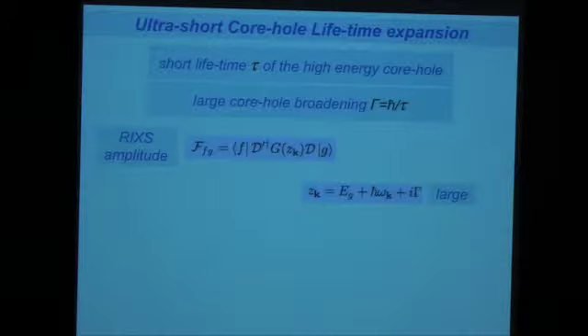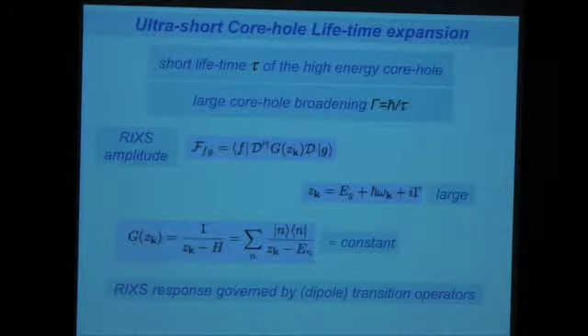If I look at the RIXS amplitude, there was this Z in the middle there, and there's my core hole lifetime from this i gamma in the amplitude. And if I'm naive, I could say, well, let's make gamma the largest energy scale in the problem. So then Z becomes large. If Z becomes large, I can neglect this En. And if I do so, now I have a summation that's just closure, and my G(Z) will be constant. It is naive, but let's use it and see what happens. Actually, much of the theory of RIXS is based on going systematically beyond this naive approximation. So in this case, my RIXS response is governed by dipole transition operators.